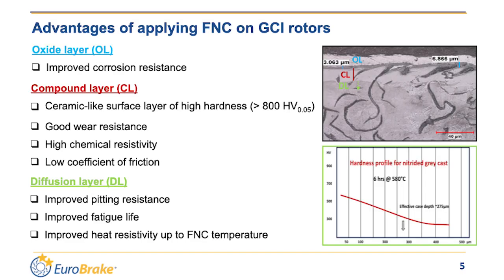What is ferritic nitrocarburizing? It's a thermochemical treatment that involves introducing nitrogen and carbon into the steel surface at elevated temperature, between 500 and 600 degrees centigrade, to enhance the performance of the steel components in terms of wear, corrosion, hardness, and fatigue, and so on.